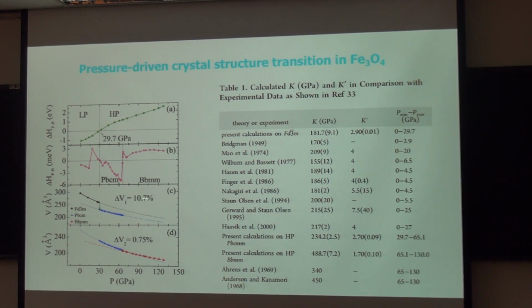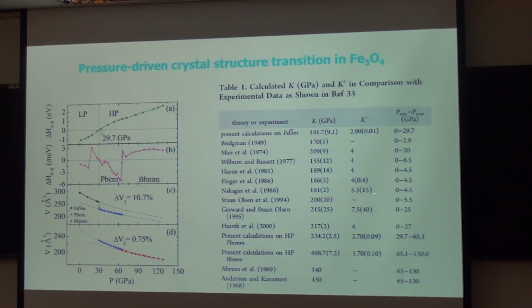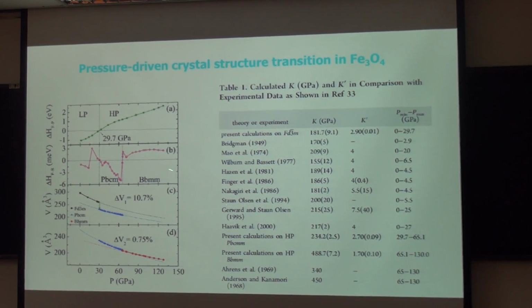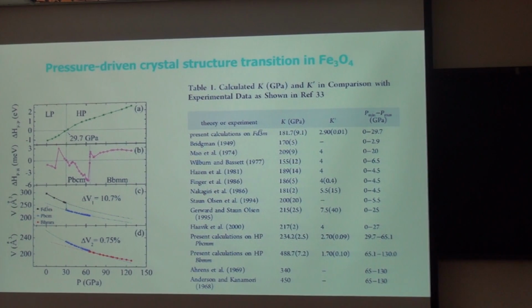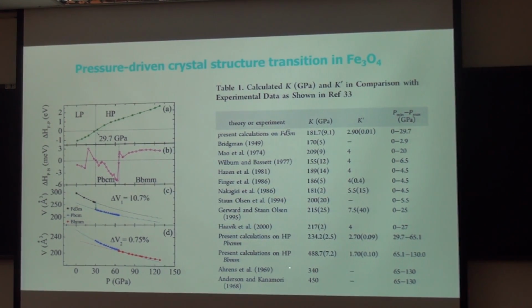We also studied the mechanical properties of these two phases and compared with experimental data in this table. We can find for the ambient phase, that is Fd-3m, the inverse spinel system, the calculated bulk modulus agrees with the experiment very well. For the high pressure phase, we can find the K increases rapidly. This is reasonable, since for the high pressure phase the bulk modulus should be large, which indicates the system is not easy to compress. For the high pressure phase, our calculated K is around 500, and its experimental value is of the same order. And so we're very confident our